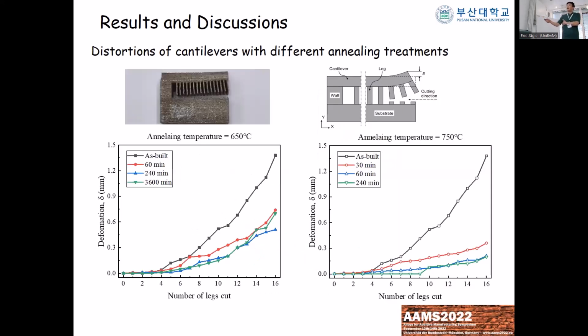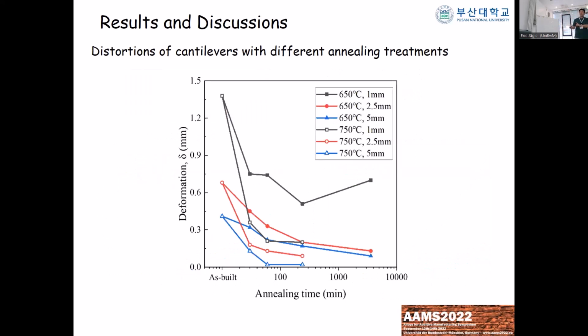So here we plot the final distortion after cutting all the legs and do the comparison. In the x-axis we have annealing time and in the y-axis we have deformation. And here the closed symbol represents the heat treatment temperature of 650 degrees C, and the open symbol is for 750 degrees C. What we could see from the previous slide, depending on the annealing time and temperature, the final distortion decreases. That means the residual stress is decreasing as expected. And another thing is that the deformation also depends on the thickness of the cantilever. That's of course because the thicker the cantilever beam is, the stiffer it is, so it's difficult to bend.